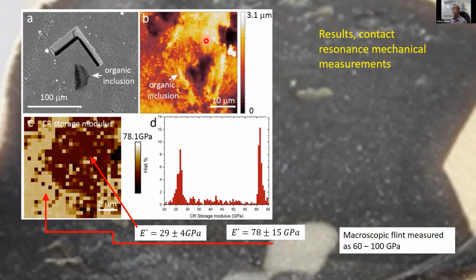We were able to find these, by the way, by correlation with these FIB marks which were made on the sample. Down here on the left, then we see the mapping of the modulus. The dark area is that microinclusion. The brighter area around it is the surrounding silicon oxide component.